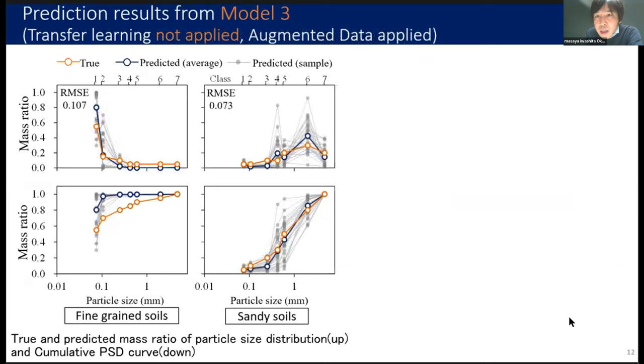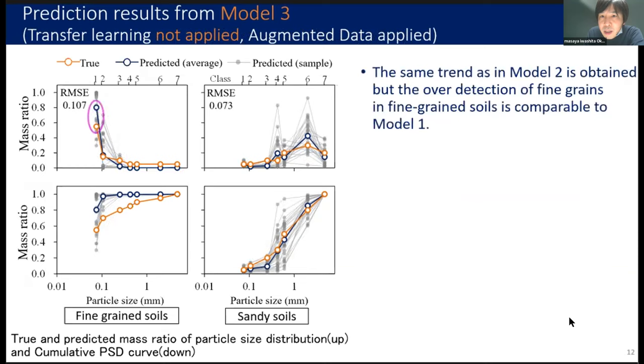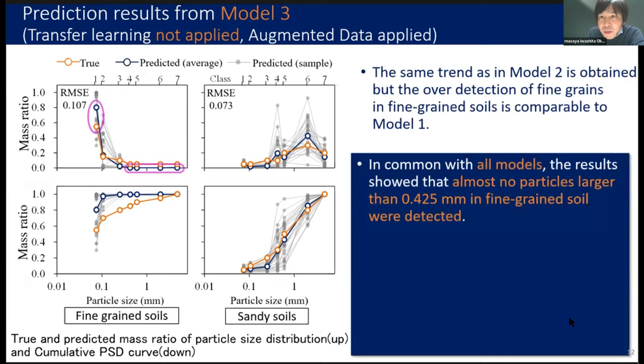Experimental results for model 3 are shown on the left. The same trends as the results of model 2 are obtained, but the overdetection of fine grains in fine-grained soil is comparable to model 1. All models overpredict the fine-grained fraction of fine-grained soil and underpredict particles larger than 0.425 millimeter. One possible reason for this is that the fine particles adhere to the larger particles.